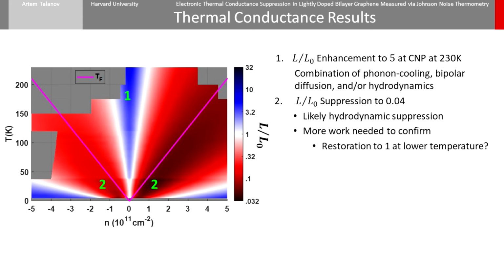The second region shows a 25-fold suppression of the Lorentz ratio to 0.04. This is likely a result of hydrodynamic transport in bilayer graphene, as such a violation of the Wiedemann-Franz law can't be caused by bipolar diffusion or phonon cooling. More work is yet needed to confirm this suppression. In particular, at lower temperatures, when the transport becomes impurity dominated, the Lorentz ratio should restore back to 1.